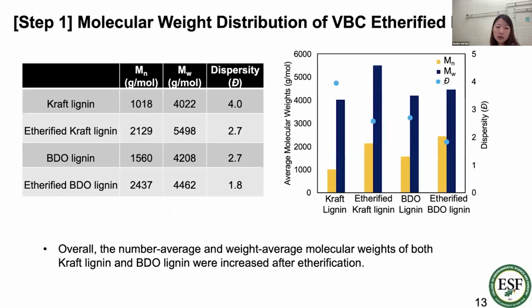And we want to see how the molecular weight distribution changed after the modification. After the modification, the molecular weight increased for both types of lignin. This result indicates that the additional functional group, the VBC structure, was successfully attached to the lignin structure.